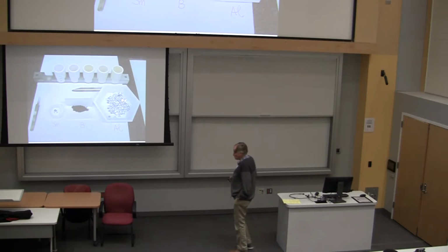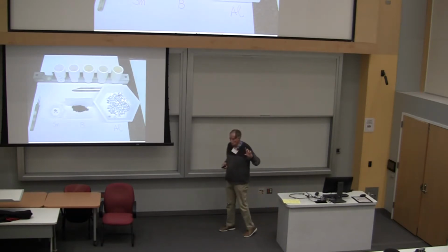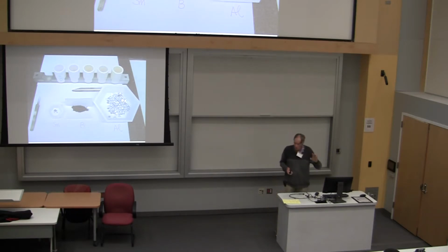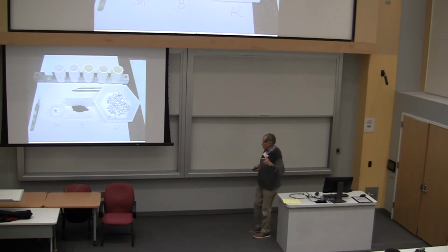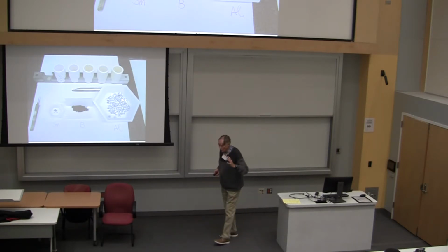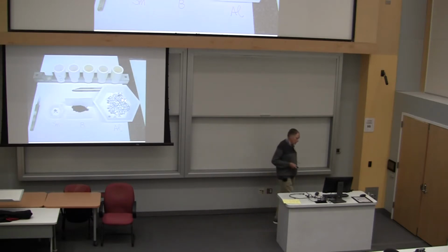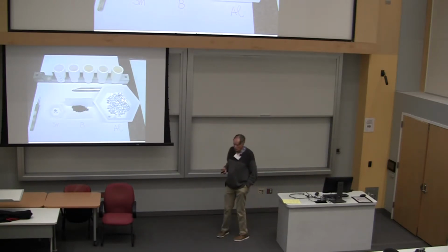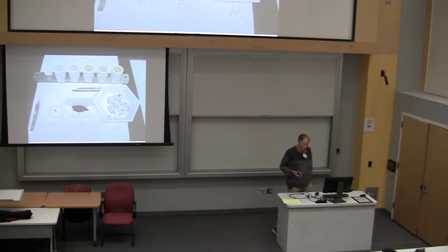That's because, okay, so what are typical growth parameters? The typical size of alumina crucibles that you can buy from Coors or McDaniel or somebody like that are 2 ml, 5 ml, and 50 ml. And for simple exploration, 2 ml crucibles are great. But the solubility of B6 in molten aluminum, you can measure by other techniques. Well, I did it originally with lanthanum B6. You can arc melt lanthanum B6. Samarium's a problem. It has a high vapor pressure, so working with an arc furnace is a bit of a nuisance.